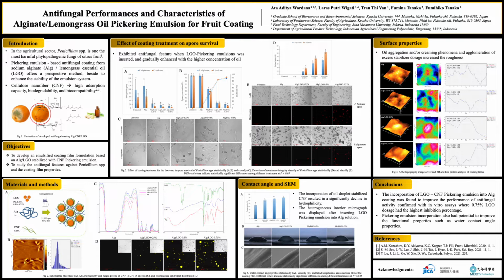The use of nanocellulose has been gaining interest due to its prospective features, including hydrophobicity and high adsorption capacity. The objective of this work is to develop an emulsified coating film formulation based on alginate and lemongrass essential oil stabilized with nanocellulose Pickering emulsion, and to study the antifungal features against Penicillium species and the coating film properties. The stabilized Pickering emulsion agent stock was prepared by dispersing cellulose nanofiber into distilled water using a high-speed homogenizer for 1 minute. At the same time, alginate solution was prepared by gelatinizing sodium alginate powder. Then all the materials were homogenized at 15,000 RPM for 2 minutes.